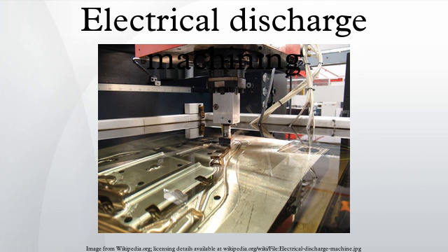On most machines, the upper guide can also move independently in the U-V axis, giving rise to the ability to cut tapered and transitioning shapes. The upper guide can control axis movements in X-Y-U-V-i-j-k-l. This allows the wire-cut EDM to be programmed to cut very intricate and delicate shapes. The upper and lower diamond guides are usually accurate to 0.004 mm, and can have a cutting path or kerf as small as 0.021 mm using a 0.02 mm wire, though the average cutting kerf that achieves the best economic cost and machining time is 0.335 mm using a 0.25 mm brass wire.